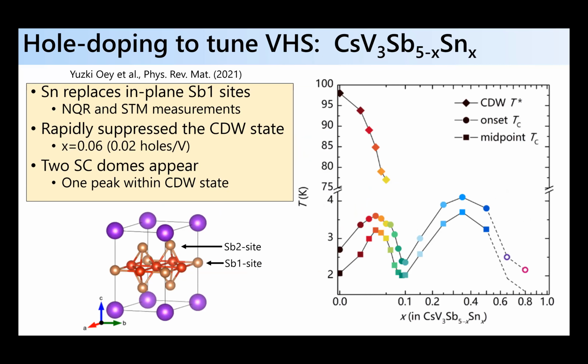Okay, so I would say the most interesting example of this is that you can hole dope the cesium compound, and when you do so, 2 kind of interesting or unexpected things occur. The first is that the charge density wave order collapses really fast. This is a square root scale, sorry, my students get creative with how to represent data. But basically it comes down rapidly at around 5% holes per formula unit. You have this first order disappearance of the thermodynamic anomaly associated with charge density wave order.